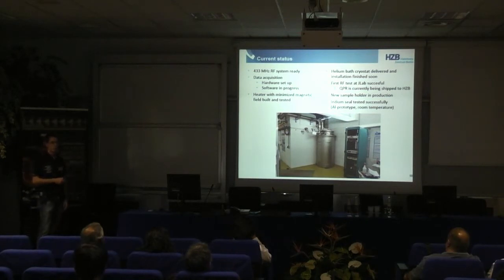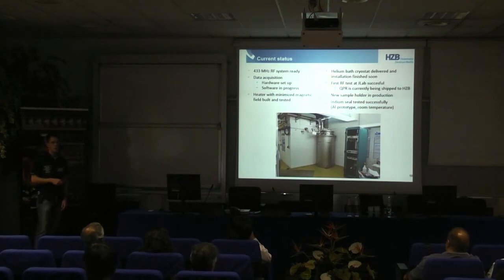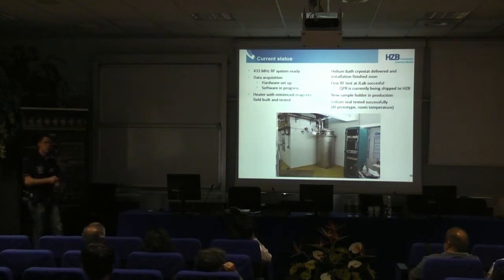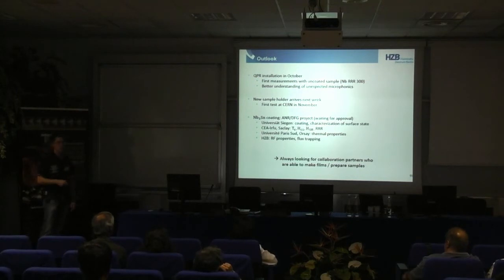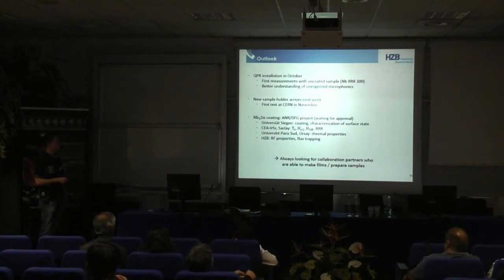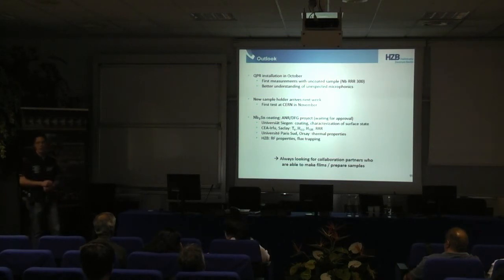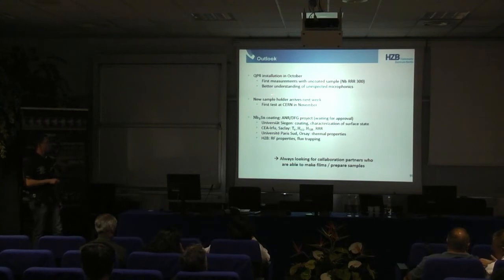The new sample holder is also in production and will hopefully be ready soon. The indium seal has been tested quite successfully with an aluminum prototype. We want to repeat these indium tests with the real niobium calorimetric chamber, because of the different thermal properties of these two materials. The QPR will be installed in October, and we'll do first measurements again with the same sample as at JLAB — an uncoated niobium cylinder with a high RRR. We hope to get a better understanding of unexpected microphonics from the first measurement.